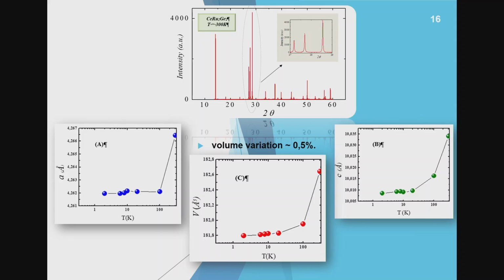And so I did an experiment in a cyclotron, trying to see if there is some shrinkage or some anomaly in the crystal structure. We did this as a function of temperature, working with Granado at LNLS. We came to the conclusion that the volume variation was only 0.5%. No anomalies were found in the lines, no difference in the lines, and this is only normal thermal contraction of the lattice. So we thought, okay, it's not a problem of lattice contraction or a change in this electric field gradient, okay?